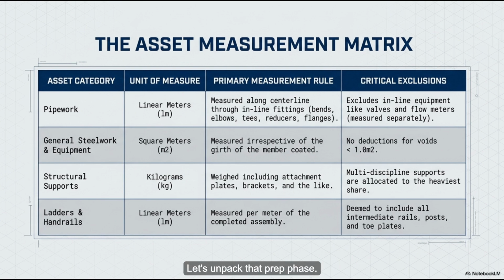Right, let's unpack that prep phase. Because the preambles mandate that the unit rate covers solvent washing to strip away machine oils, and then it's followed by abrasive blasting to take the steel all the way down to its raw state. Yep, all the way to bare metal. I'm assuming this isn't just about making the metal look clean. There has to be a mechanical necessity for blasting the steel before you put epoxy on it. Oh, there is. Heavy industrial coatings just do not stick to smooth surfaces. They just slide right off.